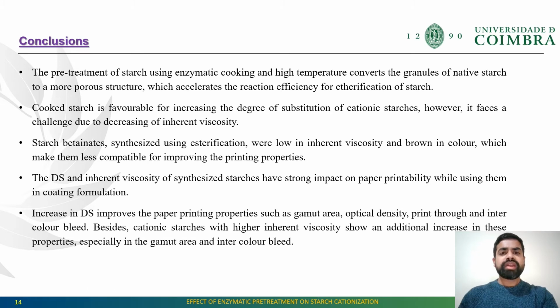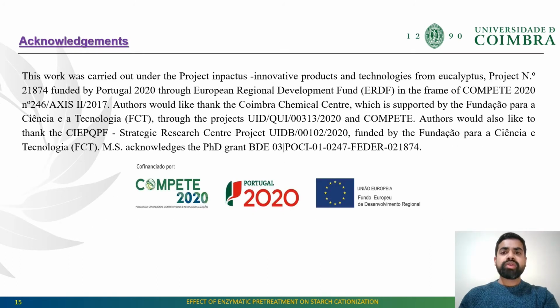The DS and inherent viscosity of synthesized cationic starches have a strong impact on paper printability when used in coating formulations. It was also found that an increase in DS improves paper printability such as gamut area, optical density, print through and inter colour bleed. Also, cationic starches with high inherent viscosity show an additional increase in properties such as gamut area and inter colour bleed.